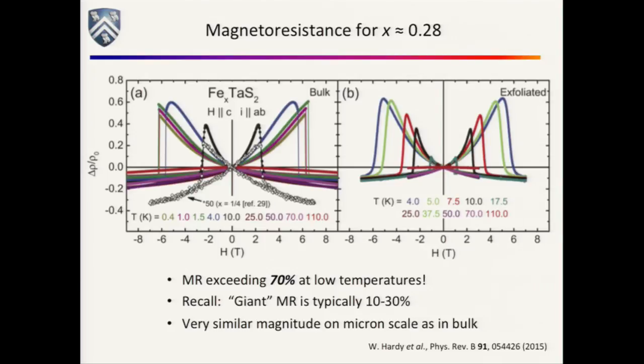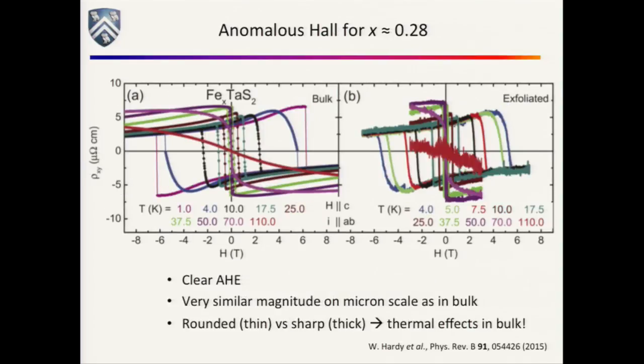We're calling this like whopping magnetoresistance in the lab, but that did not make it into the paper. And the interesting thing here is that everything looks very similar in the exfoliated piece as it does in the bulk. One thing to note, notice how in the bulk, these transitions are incredibly sharp. They're a bit more rounded in the small flake. You can do anomalous Hall, right?